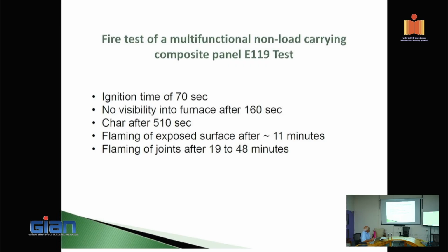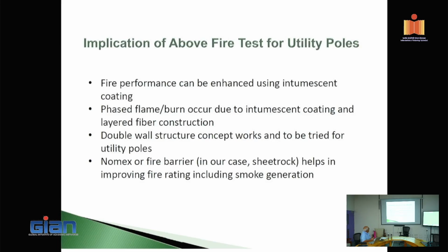So various flame of exposed surface. After 11 minutes, there is a standard for it under the E119, flame of joints. After that's a critical one. So they have standardized that stuff. So implications of the above test for the utility poles is fire performance can be enhanced using the coatings. Phased flame burn occurs due to intumescent coating and layered fiber construction. That's what I told you, 40 layers of fiber delays it up to 30 minutes. Typically, the fire ratings are based on half-hour rating, 1 hour rating, and that rating in a concrete building depends on the clear cover, like a half-inch cover is 15 minutes, 1-inch cover is half hour, 2-inch cover is 2 hours, things like that.